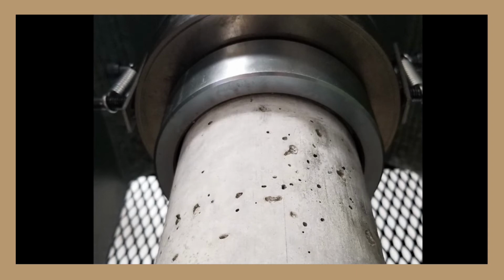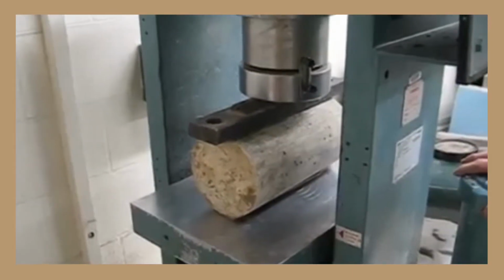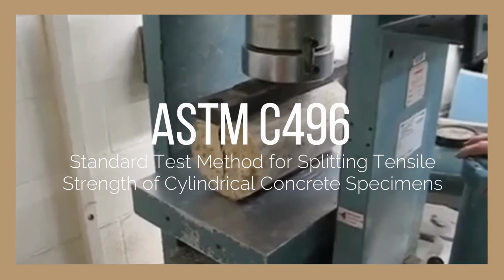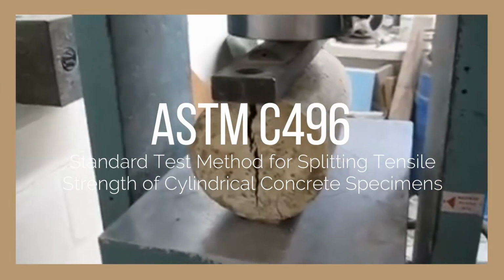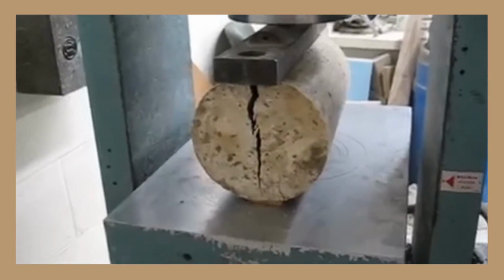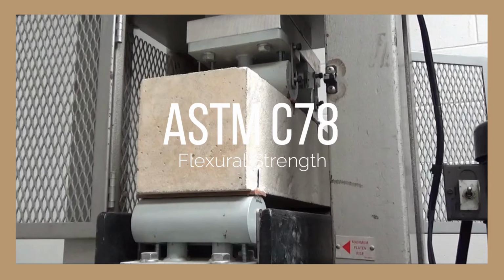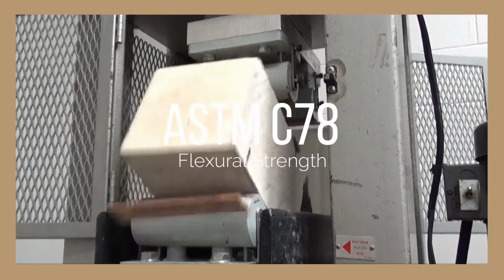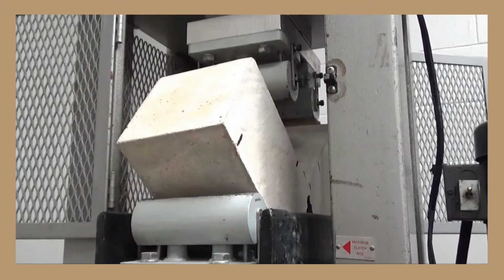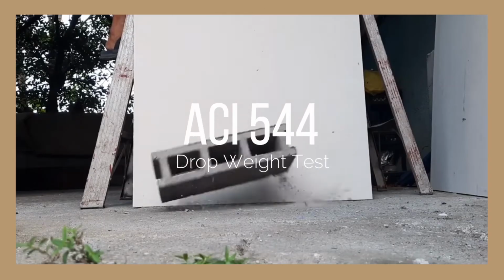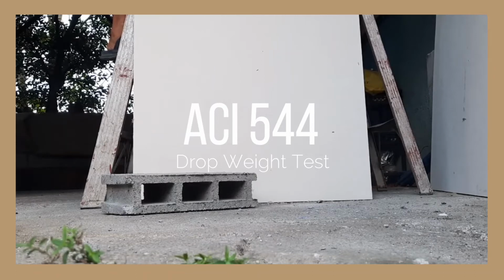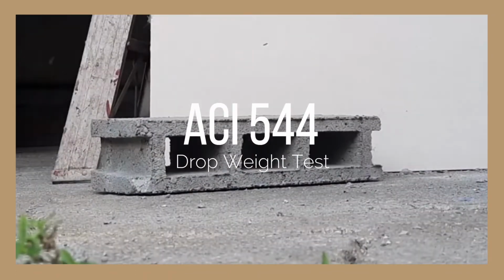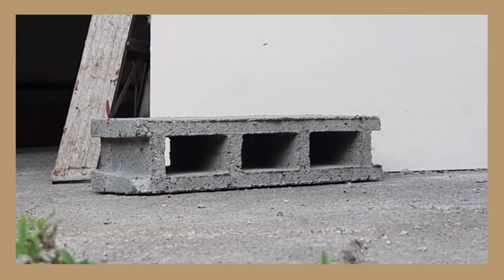It will also be tested for split tensile strength following ASTM C496, or the standard test method for splitting tensile strength of cylindrical concrete specimens. Flexural strength must be obtained using ASTM C78, known as the standard test method for flexural strength of concrete using simple beam with third point loading. And lastly, its resistance to impact will also be essential in workability, thus it will be tested through a drop weight test conforming to ACI 544.